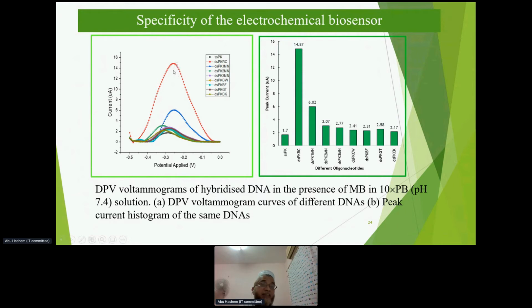From here, we clearly see that the reverse complementary DNA has a much higher peak compared to others. This is for single base mismatch, and all other DNA have very minimal peaks. This is indicated on the right hand side. This is the peak for complementary DNA. This is for single base mismatch. This is for 2, and this is for 3. All other DNA are similar to probe DNA only.